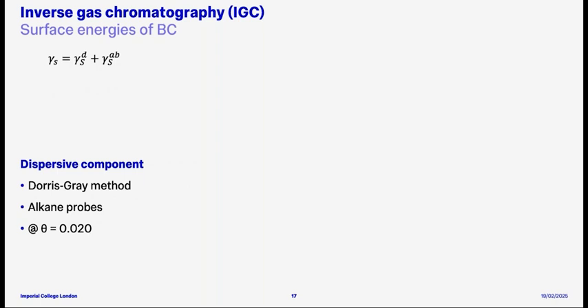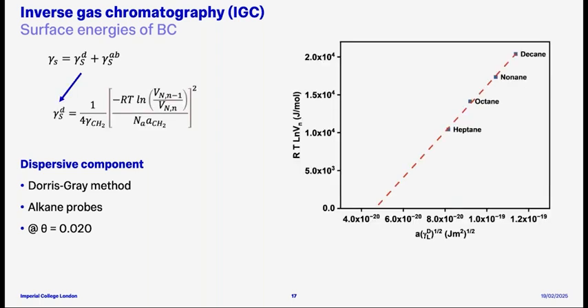So the surface energetics of bacterial cellulose at infinite dilution was first determined. By knowing the retention volumes of different n-alkane probes, the dispersive components can be calculated and determined from the linear slope of this plot on the right. The dispersive component of bacterial cellulose was measured to be around 60 millijoules per square meter, which is very similar to values reported by others in literature.